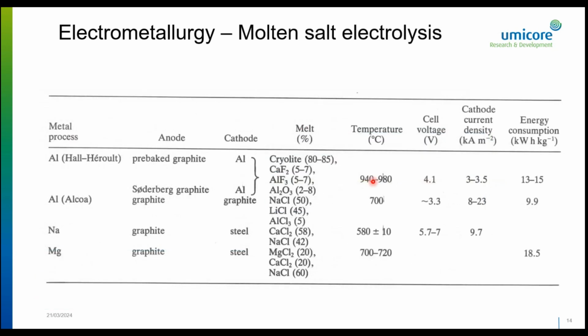Then first I'm going to talk about molten salt electrolysis. So these are the metals with a very low reduction potential. So these are processed in molten salt media, for instance, aluminum, sodium, magnesium. You can see here this is done at very high temperatures, so let's say between 500 and 1000 degrees Celsius. This doesn't look too familiar probably, but I just want to show that the current densities that we're working at are very high. You don't have a comparison right now, but you'll see if I compare it to, for instance, electrowinning, that the current densities are very high, so let's say definitely above 1000 amps per square meter.